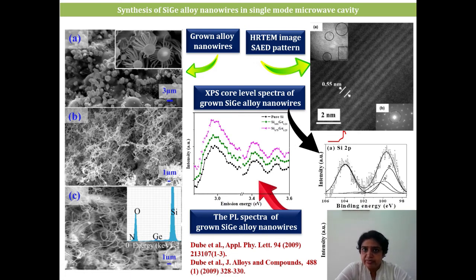So from HRTEM we saw the core is very crystalline, that is silicon germanium alloy nanowire, and the spacing between the fringes corresponded to the alloy nanowire. However, these results reveal that there is some kind of oxide formation on the surface. So oxide is on the surface, and inside is the core; the shell is to some extent oxide, and the core was crystalline silicon germanium alloy. And then we did EDX measurement also, and we got the same information from the EDX, and we took PL spectra, and what we found is that these grown alloy nanowires are very good emitters. So basically defects in the oxide have resulted in this kind of emission.